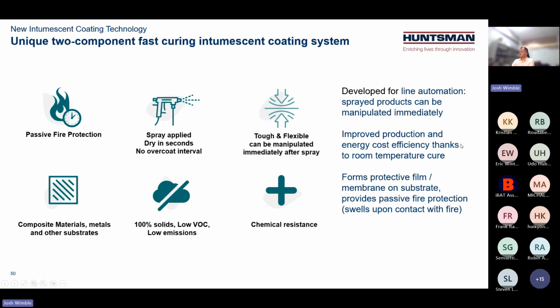One last technology I'll mention that's emerging as a priority for some development teams with the changing requirements around thermal runaway in China. To give a bit of context, I think a few people have heard there's this proposal in China to move from what's typically globally anywhere from 5 to 15 minutes of escape time to up to 2 hours of escape time, where a battery has to completely contain a thermal runaway event for 2 hours. It's a pretty significant jump. And so the industry is looking at a variety of technologies that can help support this.